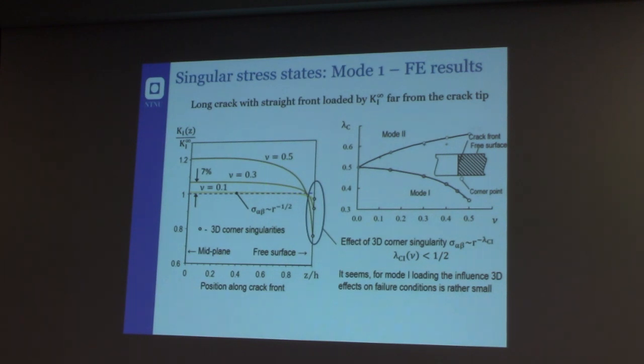If you have 0.5, that is very difficult to have. But if you are in the condition of a polymer, for example 0.4, you have an increase of 15% or more in terms of the stress intensity factor. So also here it's not negligible, and you have to consider this effect.